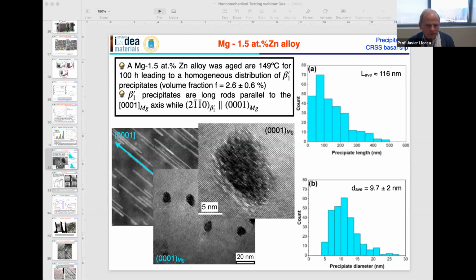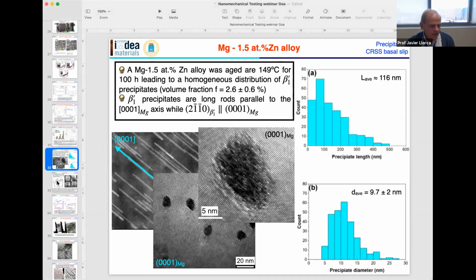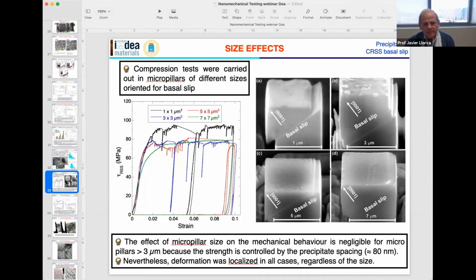When you go to high resolution, this is the basal plane, and these rods are perpendicular to the basal plane. We were able to measure that the length of these precipitates is about 100 nanometers, and the diameter, as I said before, is of the order of 10 nanometers. So we took micropillars of these materials that are well oriented for basal slip and did compression tests. These are the resolved shear stresses as a function of strain for pillars with different dimensions: 1 by 1, 3 by 3, 5 by 5, 7 by 7.